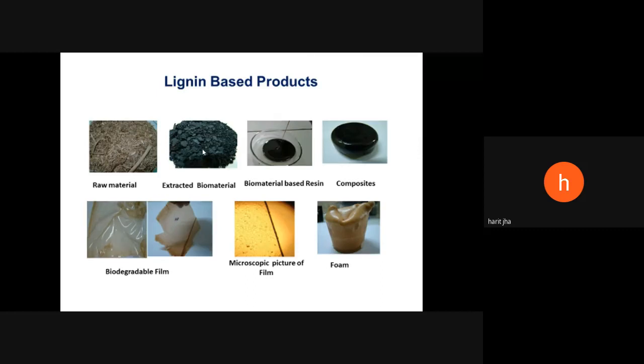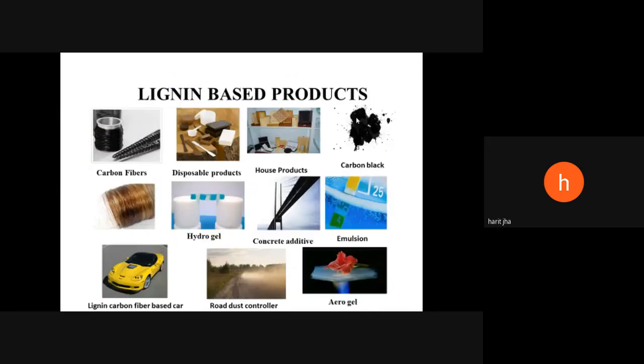Raw materials and extracted biomaterial-based resins, foams, films, etc. These are commercially available, some of which take forms like carbon fiber, lignin carbon fiber-based cars, road dust controller, and aerogel. They are extremely light. Concrete additives are also possible because lignin has a tendency to bind with calcium and metal ions, so it can inhibit fracture formation. We have already seen that they can be converted to carbon black and hydrogel, etc., and disposable materials which can be used. Thank you.